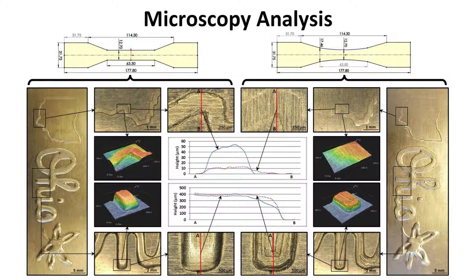Using the knowledge of these varying pressure distributions, the embossing operation was conducted with both foil geometries. The resulting embossing quality was examined using an optical microscope, and the dimensions of the corresponding feature heights were measured using multi-image depth composition techniques. The results for the single path foil are shown on the left, where features near the foil end and foil center are magnified. The same regions were also examined for the single point foil results, which are shown on the right. The three-dimensional reconstructed images allowed for the measurement of the embossed features, as plotted on the graphs in the center.